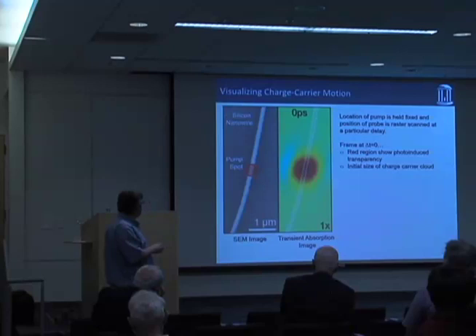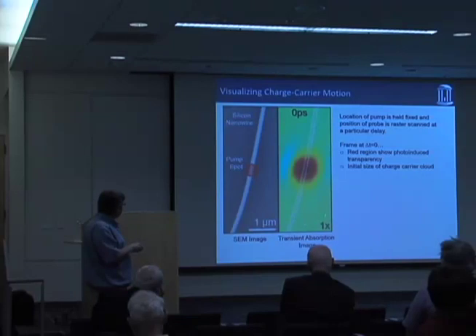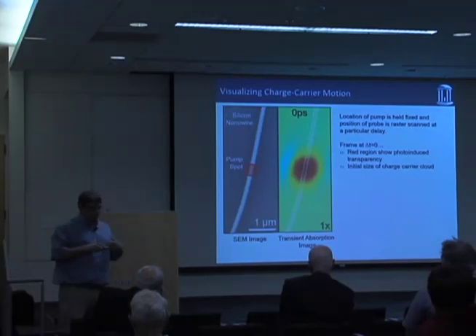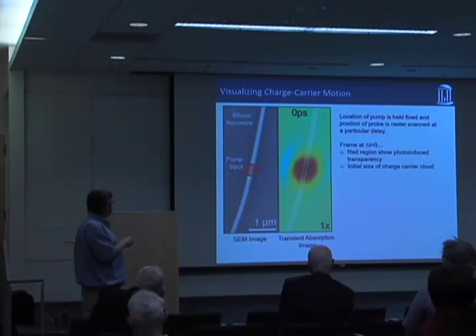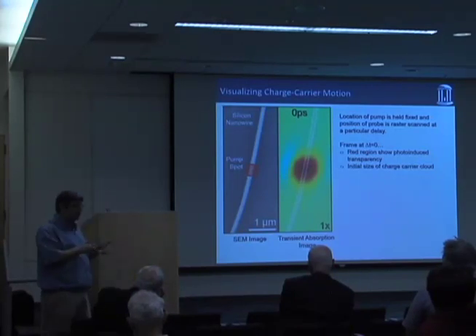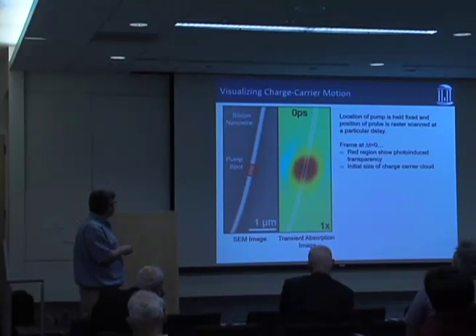So here's the image that you get at 0 picoseconds, when the pump and the probe are both overlapped in the wire. Green in this color scale corresponds to 0 signal. So when my pump and my probe are far separated from each other, I have no absorption, which is a good thing. This light thing here is a representation of where the nanowire is. The red in these images corresponds to increased transparency. So this image is essentially a spatial map of the size of the transparency created by the pump spot. It's larger in diameter than the nanowire because our spatial resolution is about 300 to 400 nanometers, and the nanowire is only about 100 nanometers.